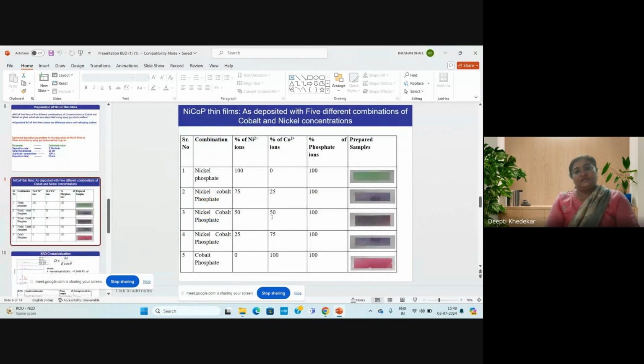These are the combinations, and prepared sample images are shown in this slide. XRD characterization we performed for all the films. We get the average crystallite size for each film. This is 26.16 nanometer for 100% nickel. For nickel 75%, cobalt 25%, it is 26.36 nanometer. Then nickel 50%, cobalt 50%, we got 28.64 nanometer.